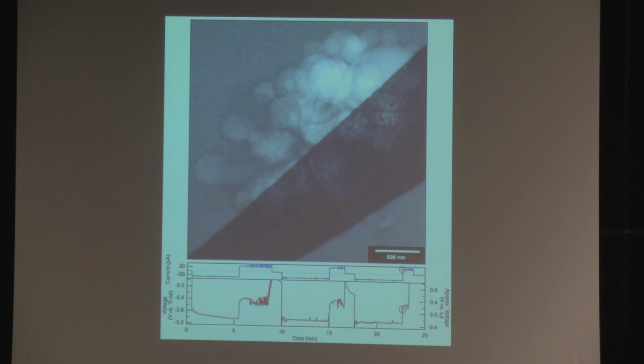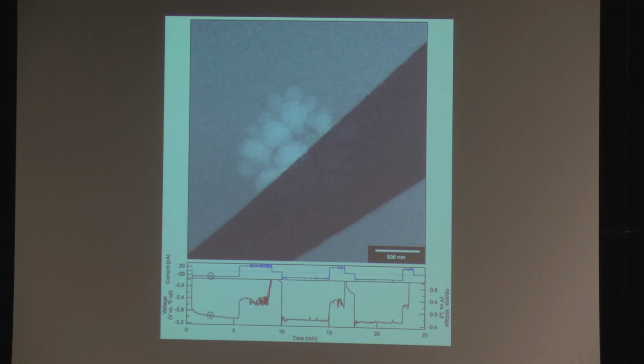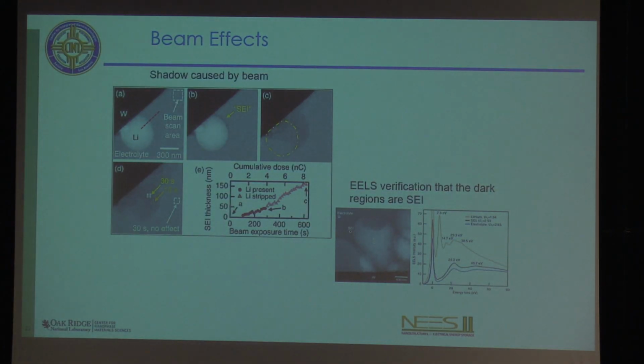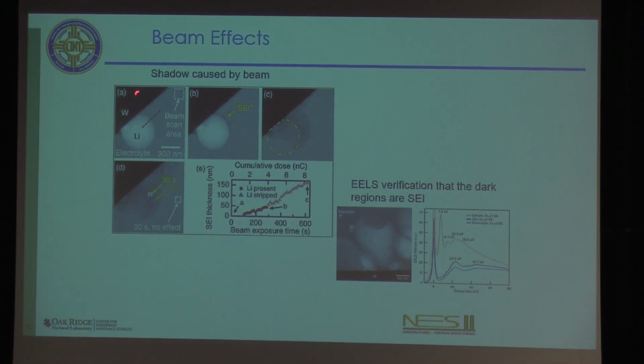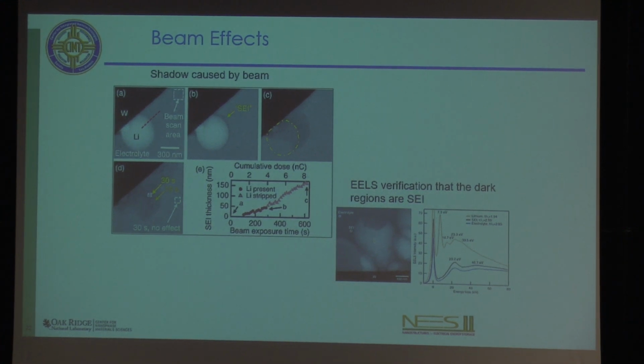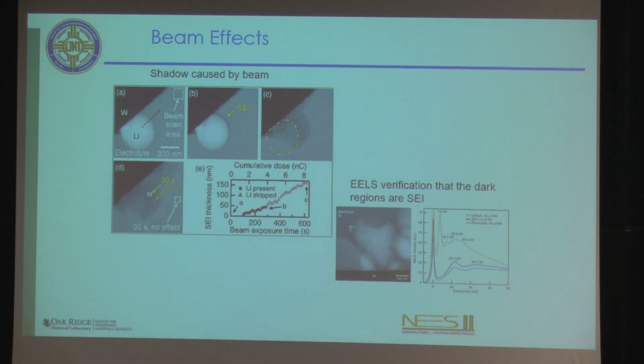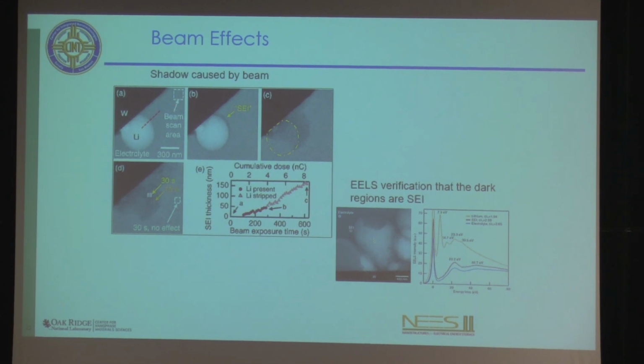So a very obvious impact that the beam is having on the deposition. Initially you saw just a globe that was formed, a very uniform structure. And when you did the plating, taking more images, you have a much higher impact on the structure. All right, so let's look a little bit more at this beam effect. Here again is a nice globe of lithium that was deposited. This had a few cycles where they deposited and stripped and deposited and stripped. The beam wasn't on initially. Then they actually did a series where they deposited the lithium, focused the beam in a corner, and waited.